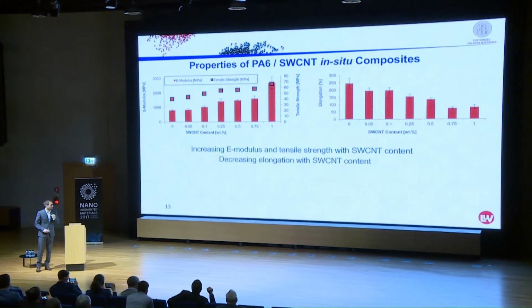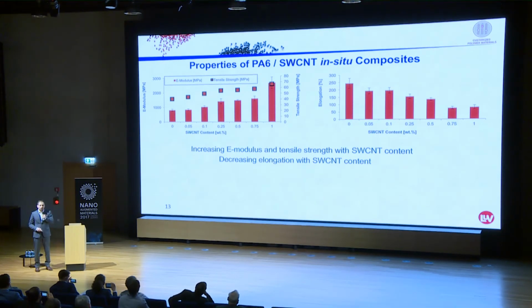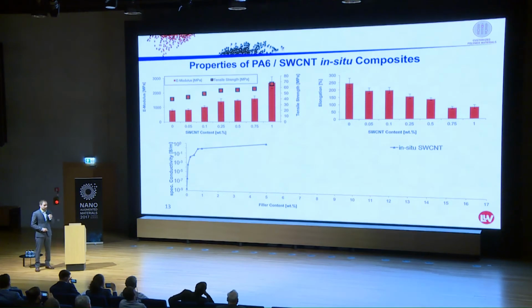What is happening with the elongation? It's decreasing with the filler content. This is what we expected, but the decrease, I have to say, is not so dramatic. We still have really, really good flexibility compared to the extrusion compounds, and especially if we compare this flexibility with the electrical conductivity of this product.